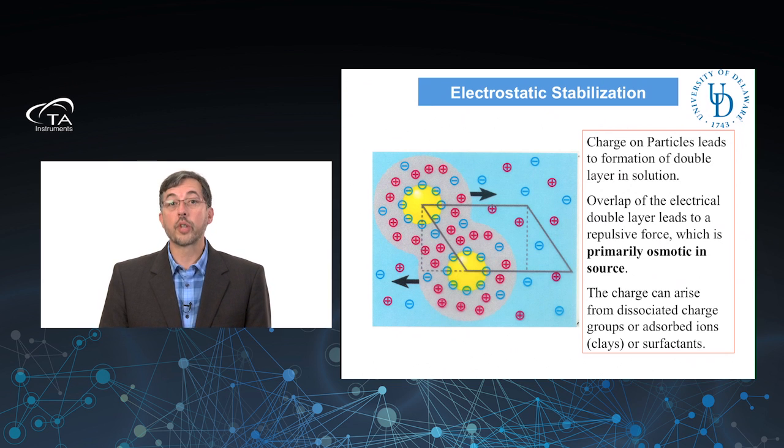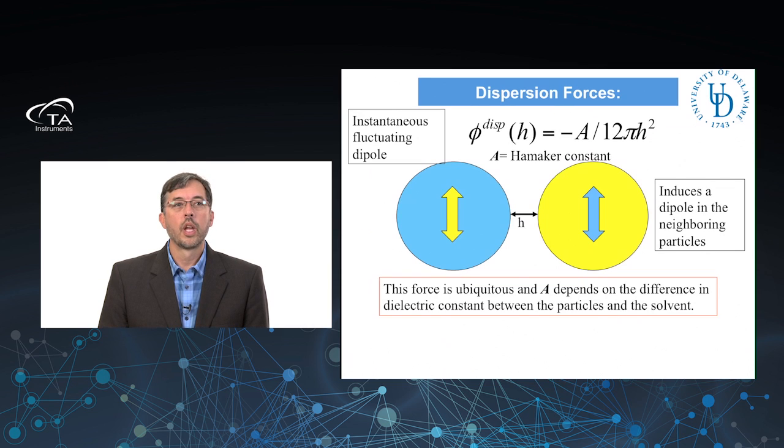When two colloidal particles come close together, those double layers, as they're called, overlap. And what you see is, of course, an electrostatic repulsion, because two like-charged objects like to repel each other due to the overlap of that electric field. But there's also an effect, essentially, due to the osmotic pressure that's created by having a concentration of those counterions in between the two gold particles. Either way, that leads to a relatively large force that tends to stabilize and keep the particles apart and keep them from aggregating.